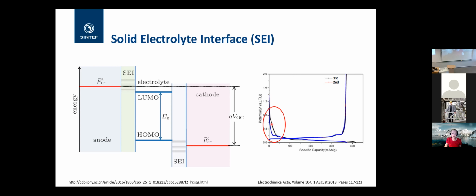For the lithium titanate that I mentioned previously, it charges at a very different potential. It's at about 1.5 volts, meaning that you stay within the electrochemical stability window of the electrolyte, and you avoid decomposition of the electrolyte, which is why it's often used in applications where safety is a big issue, because the SEI can also become unstable. It consumes lithium, and over time it deteriorates the properties of your battery.